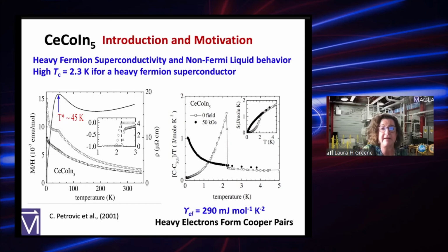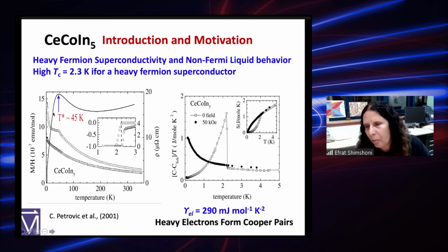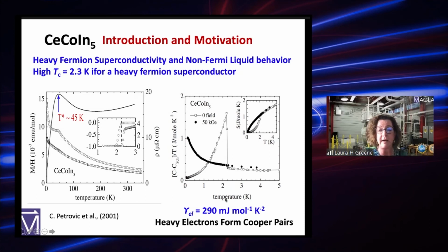It's about 85. M star is about 85 times the free electron mass. And from looking at the specific heat, we can see by this value here that the electrons that go into the superconducting phase from the specific heat are the heavy electrons. If there's a better expert on specific heat, if you want to break in, I would appreciate it.